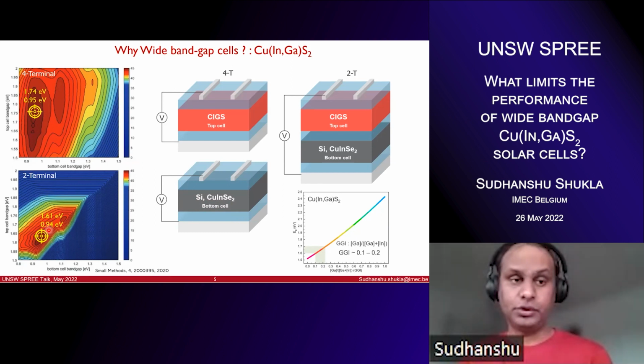Also in the case of a two-terminal solar cell, which is depicted on the right, when they are monolithically integrated, then the wide band gap top cell has to be about 1.6 eV. The good thing is that we have the bottom cells that we know today. They are very efficient, for example silicon, or if you're talking about thin films, CIS, copper indium diselenide. But what we are lacking today is the top cell, a wide band gap, 1.6 eV to 1.7 eV top absorber.